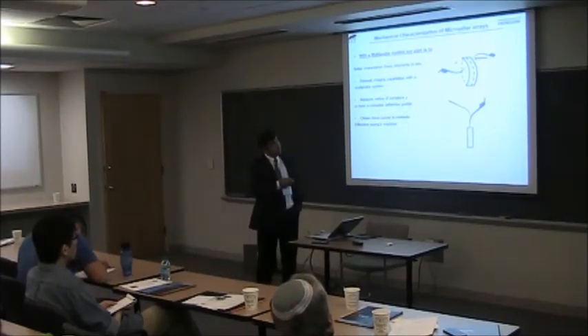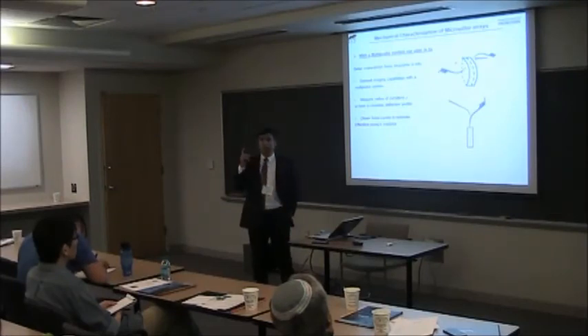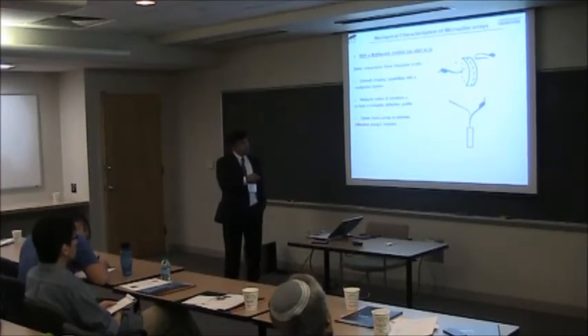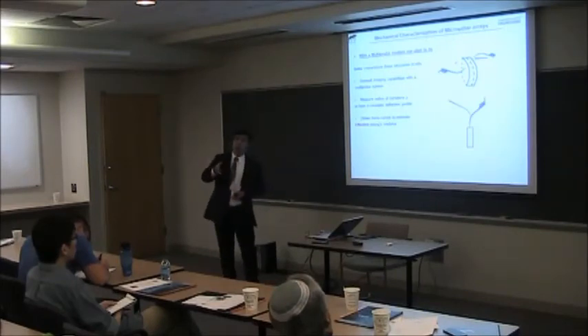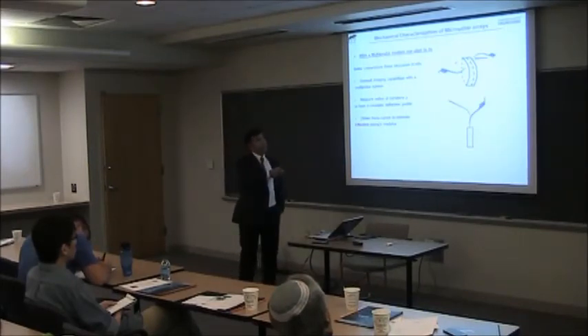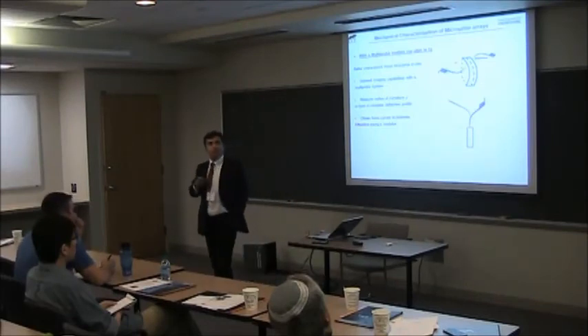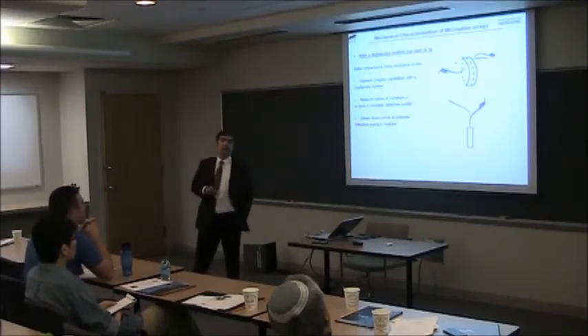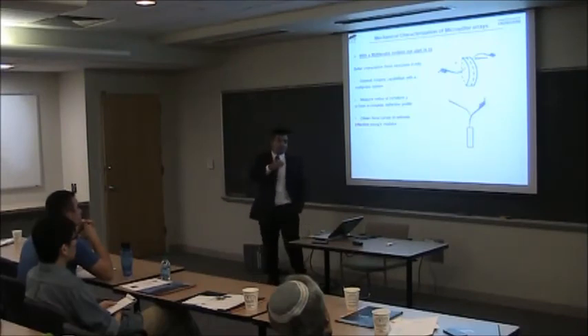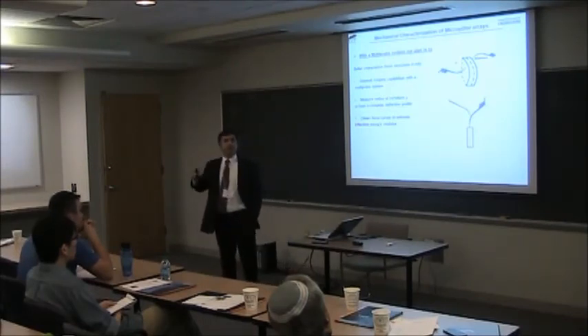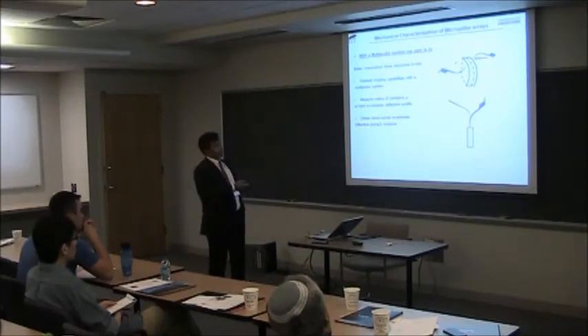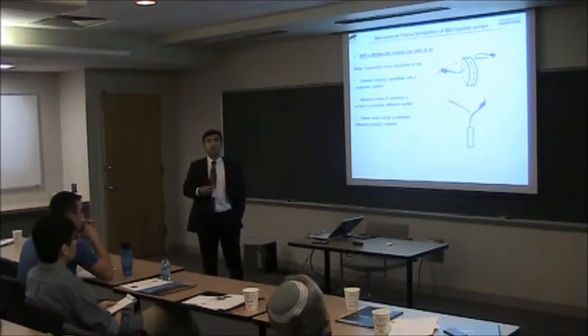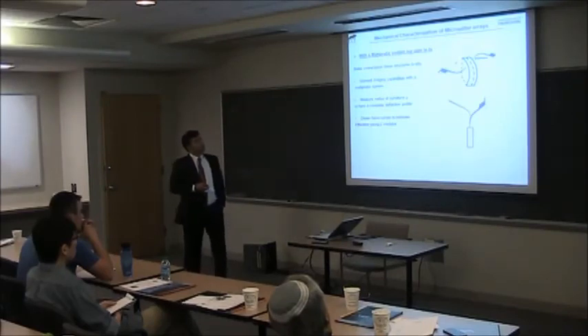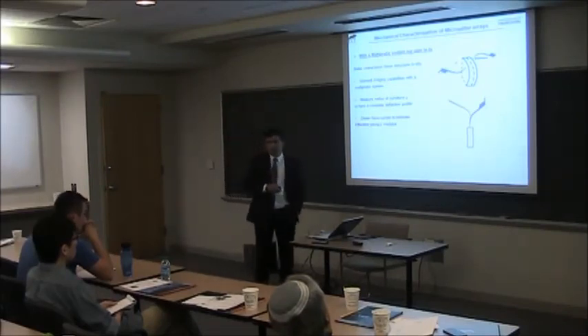First, the force that you are applying has to be known with good precision. Second, this is a soft material and the tip is touching it, so the system has to detect the z equals 0 point very precisely. And as Dalia was mentioning today, if you have high frequencies, you may not get good readings. So we are waiting to see how this will work. But we would like to do this too.